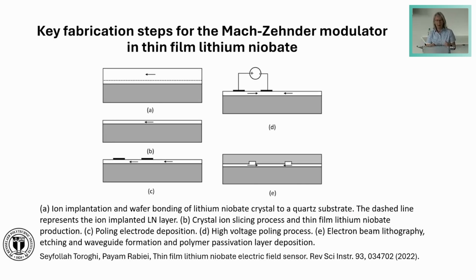The thin film lithium niobate is fabricated really from bulk crystals. So it is possible bulk crystals can be grown with really high optical quality, single crystals. And then the way the thin layers are fabricated is that the bulk crystal is ion implanted. At the specified depths, which usually corresponds to the thickness of the thin film layer, the crystalline structure is disturbed by ion implantation.